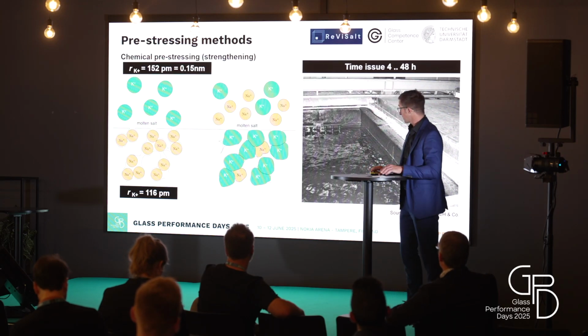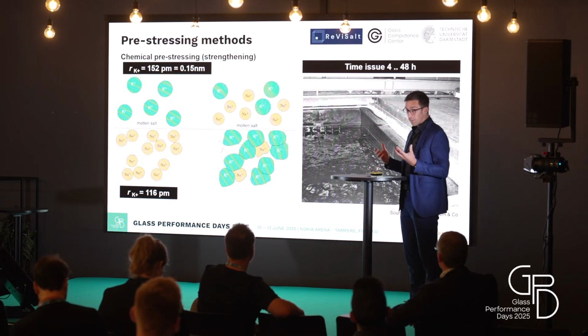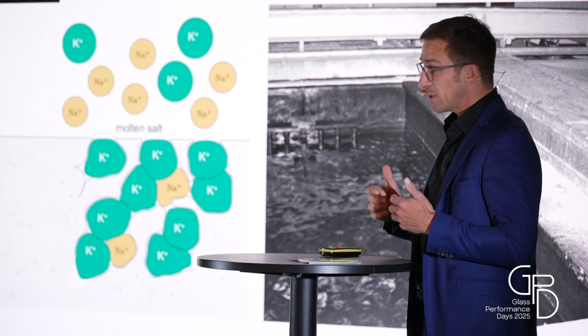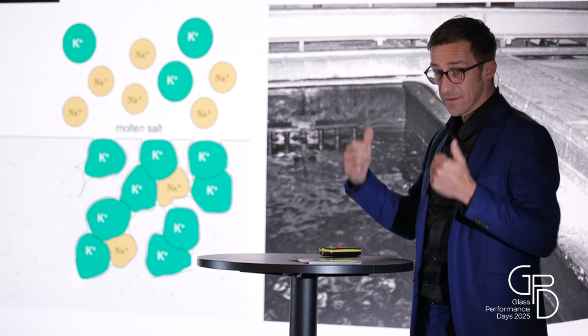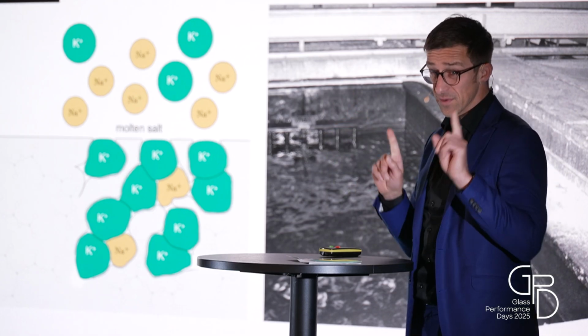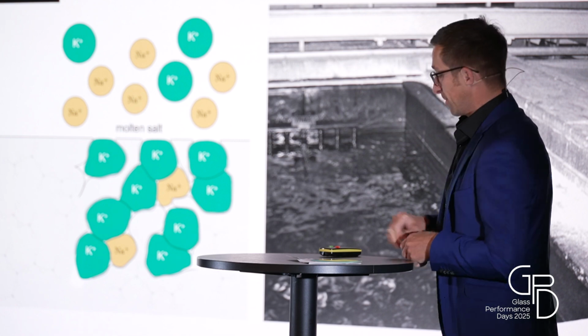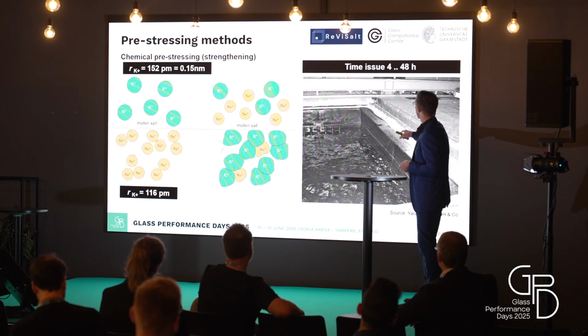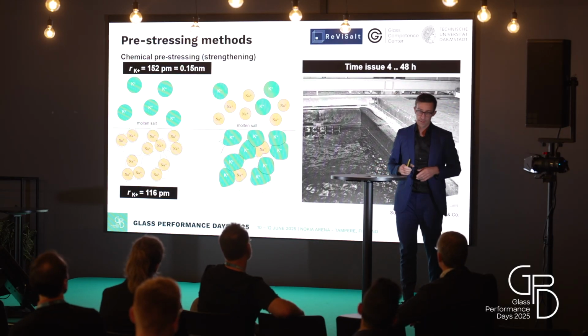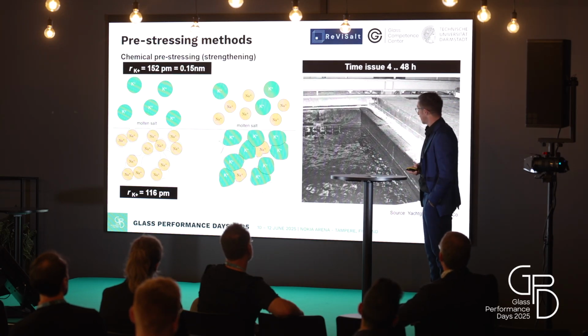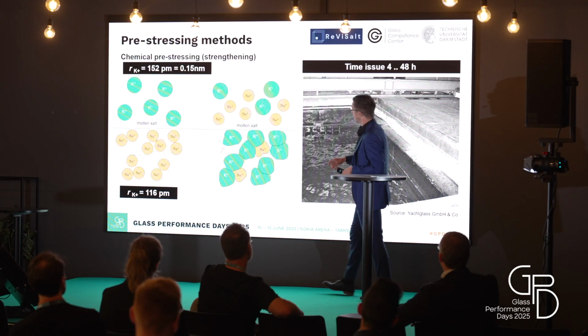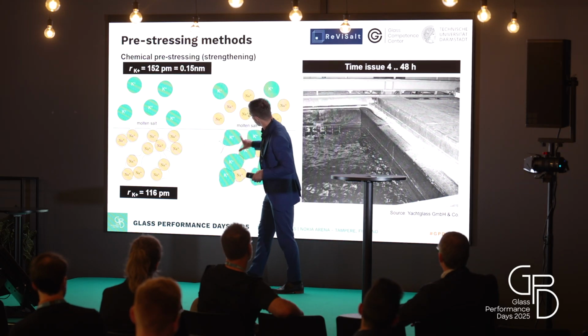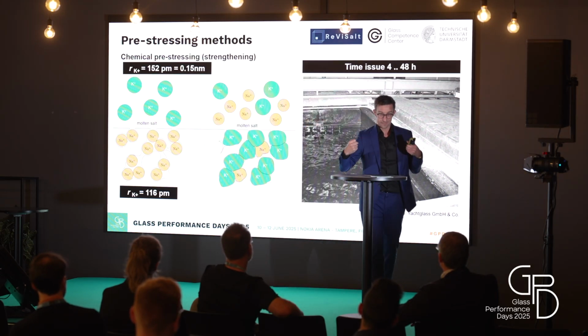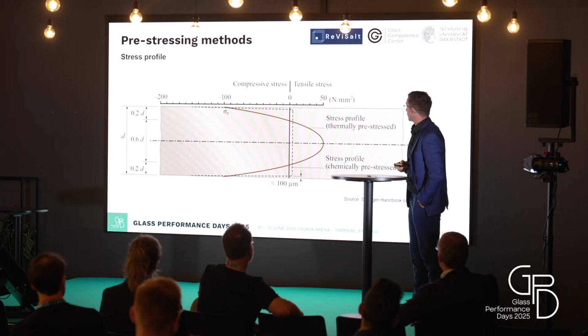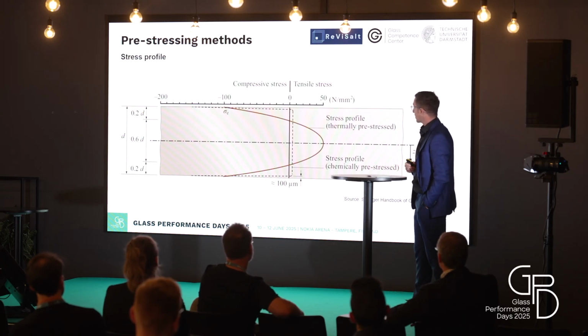Ion exchange process is a diffusion process. It works very well. The quality is also very good. We can reach really high values and strengths, up to 600 megapascal for soda lime glass, but it takes time. Minimum, I would say 4 hours up to 2 days. And this is really costly. And here you can calculate a little bit, the depth of the pre-stress region is not so high. This is also a big disadvantage of the chemical tempering.